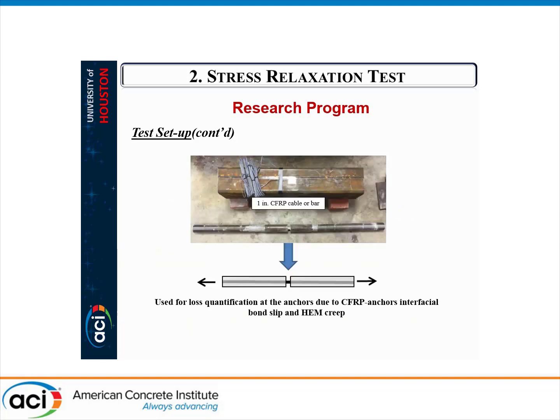Also, we conducted the same process on the very short specimens, the anchorage specimens, including the 2 sockets and a small gap between them to be able to fill the expansive material. And the same process was also repeated to measure the anchorage losses.